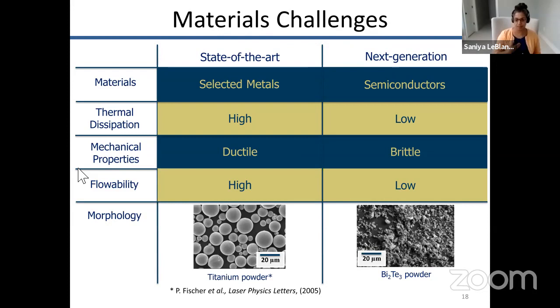With thermoelectric materials, it's kind of different. These are semiconductor materials that are designed for the thermal dissipation to be low. We want a low thermal conductivity. And the materials, they're mechanically more like a ceramic, so they're brittle materials. And then you can see an example of a scanning electron micrograph in the bottom right there. These are non-spherical powders, so when you start with the starting material, it's not spherical.